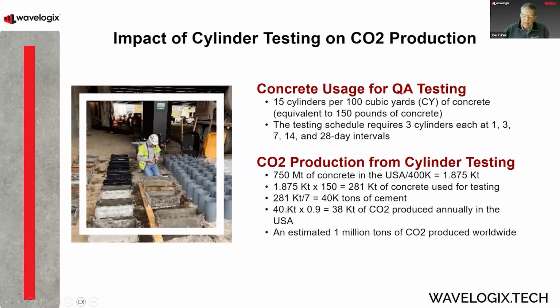If you look at the impact of those cylinders that we're using for testing purposes, we produce about 15 cylinders for every 100 cubic yards of concrete. Of those 15 cylinders, usually 3 cylinders are broken at 1, 3, 7, 14, and 28-day intervals. They represent about 150 pounds of concrete per test.